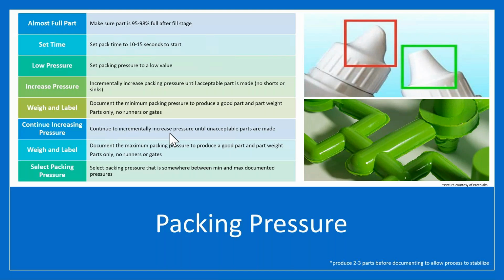until we no longer make acceptable parts, either dimensionally out of tolerance on weight, or we start flashing the cavity with angel hair, which is the first onset of parting line flash. It's very thin, very wispy. It's not a gross flashing of the cavity. It's just a small line that starts on the parting line. So as soon as we've hit that point, that's the top of our window. Weigh and label,